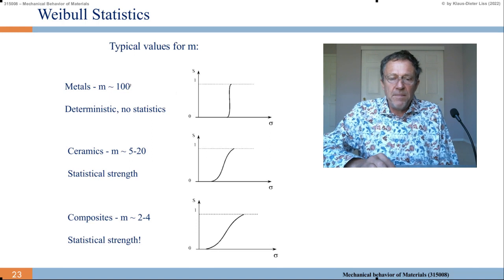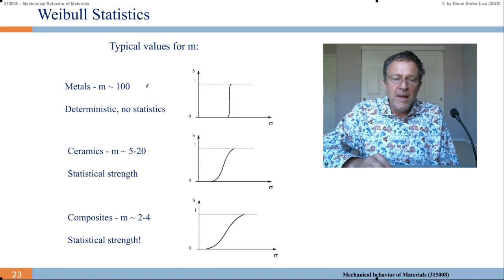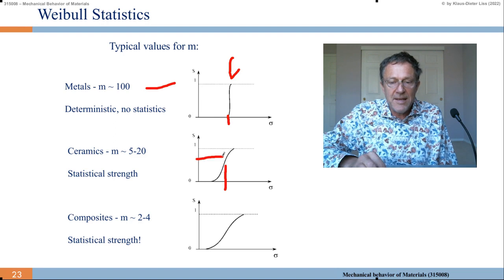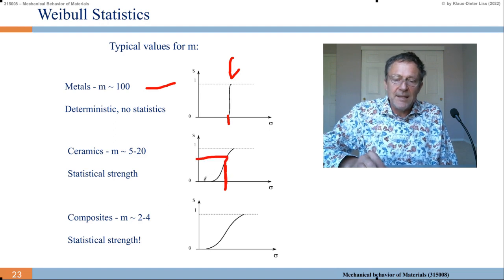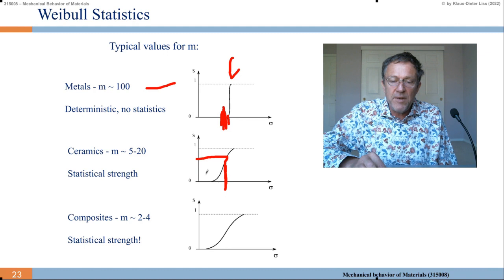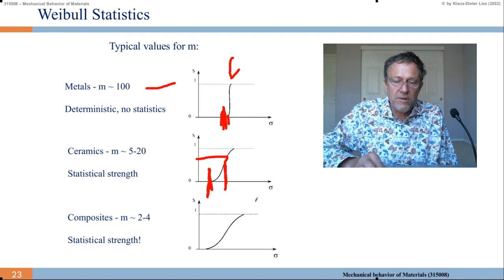Here are typical values for m. Just repeat what I said before. For metals, the m is around 100 and the curve looks like this. So this is the probability of survival now, of failure, which is 0, no failure at low stresses, and failure if you go above this value, sigma 0. For ceramics, it's 5 to 20. So if this is sigma 0, or sigma 0 is a 63% here, then we get this distribution. So here we can go in our design close to sigma 0. Here we have to be quite a bit away, maybe half sigma 0. You have to work it out, the probability of failure you want to have, yeah?